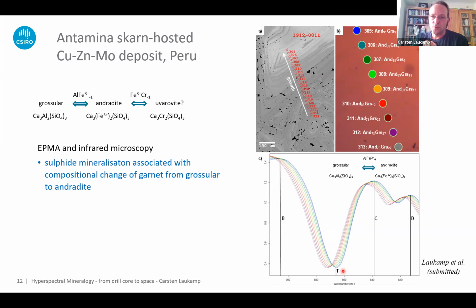And the shift of these absorption features is due to different cation environments of the silica oxygen tetrahedra in this case. So we're replacing aluminium by iron. There's a typo here. And that basically induces the wavelength shift. And we can track the compositional variation of the garnet. And we found that the sulfide mineralization is associated with compositional change of the garnet from grossular to andradite. So later stage andradite, and that's when the sulfides are coming in.